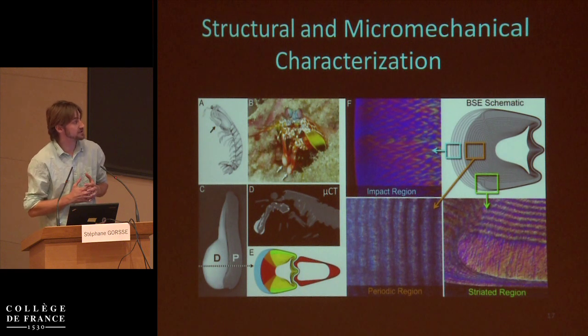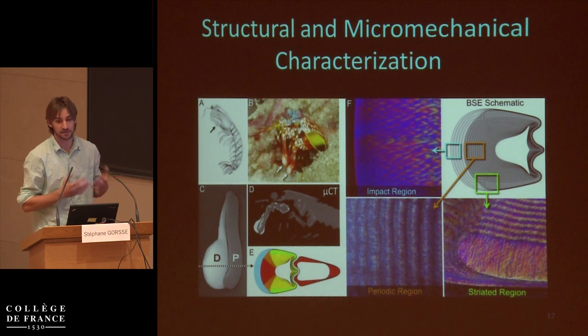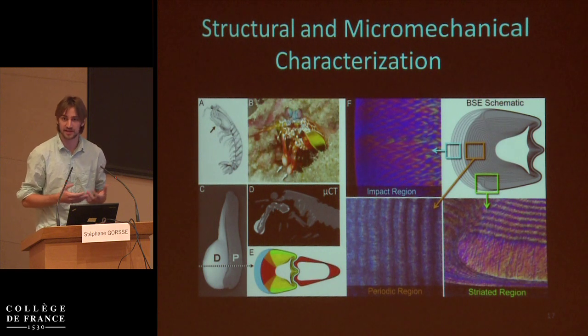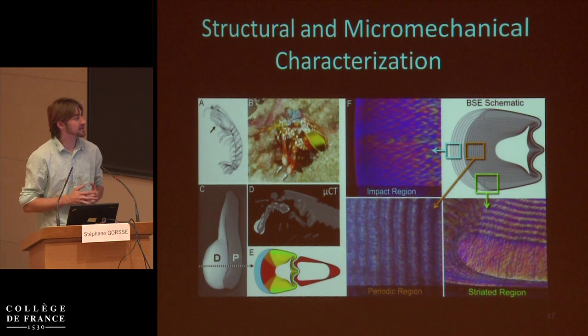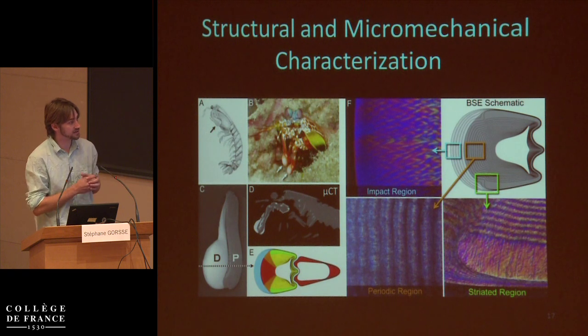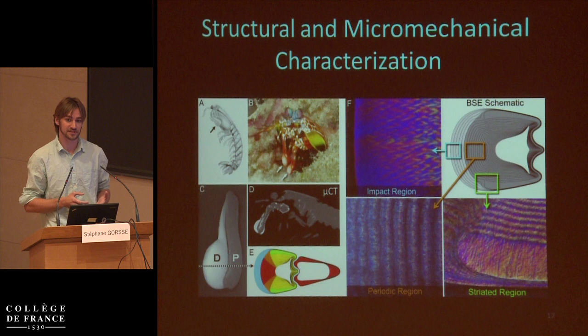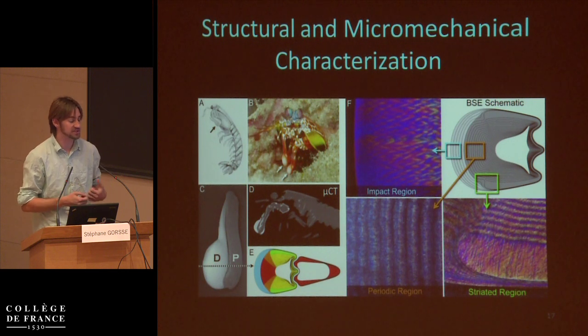because I find it to be one of the most interesting challenges, in that the impact region has got to be hard. And we actually know pretty decently how to make hard materials. But the periodic region is where the failure would form and nucleate. And so this material has to be very tough. And toughness is very difficult, especially when you're receiving tensile forces.